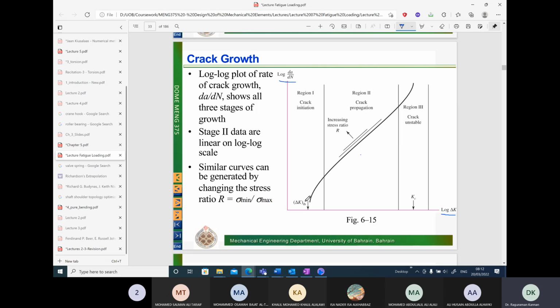On the x-axis, you have delta K value, which is this particular value. Now what you observe here is there are three stages in which the crack grows. Initially, the rate of growth of crack is very high at region 1, and then it flattens out, becoming a constant rate of crack growth in stage 2, and finally we have again exponential increase in the crack growth and then fracture. So the life of the specimen is decided between this range.